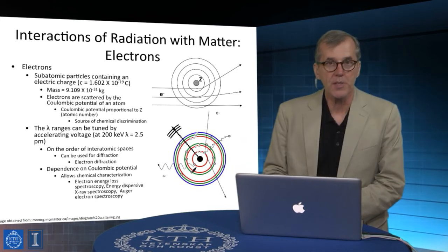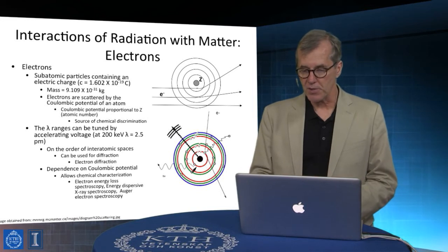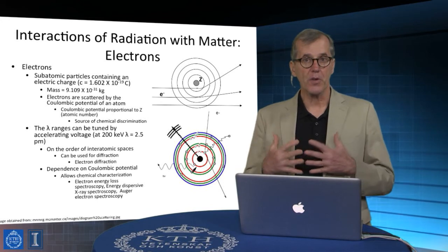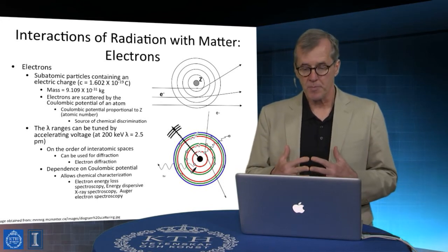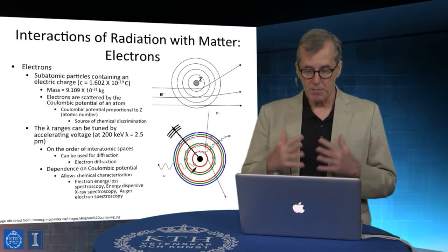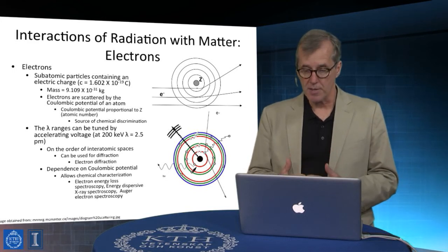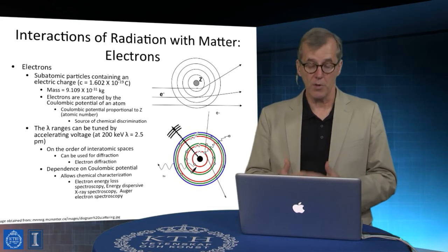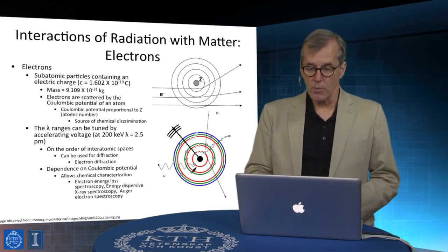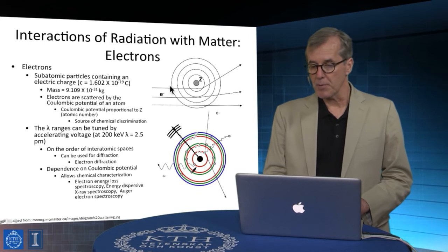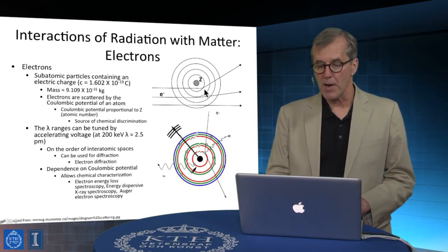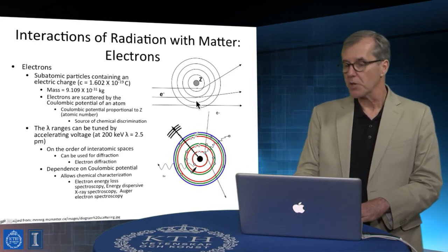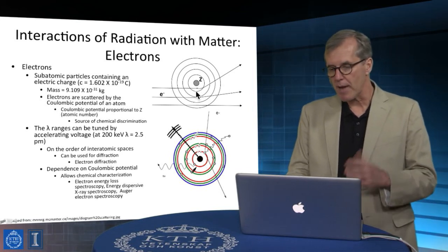The other thing we should note is that the scattering events in this case are not like X-rays. X-rays see the electric field associated with the electrons, and electrons in this case being used as a probe more or less see the Coulombic fields associated with the nuclear charge. And we see on the slide an example of scattering events determined by where the electron trajectory is relative to the shell structure, in a schematic form, of an atom.